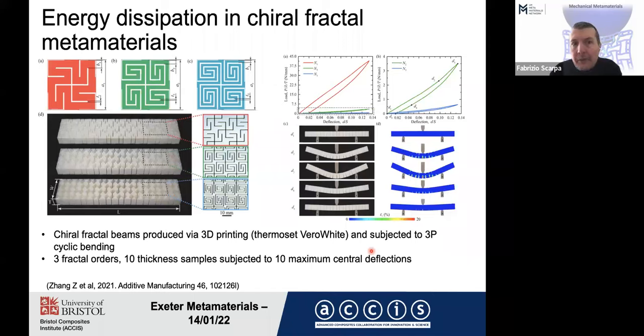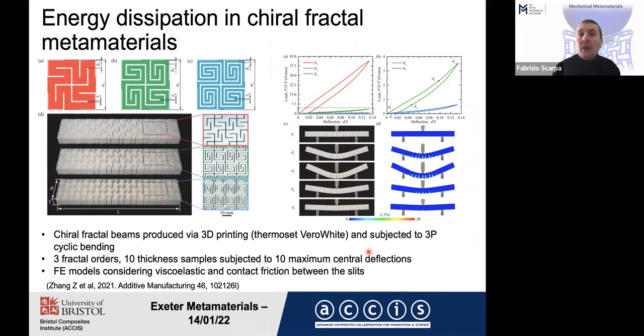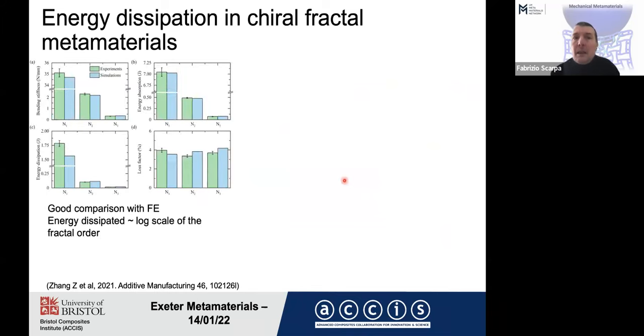We have considered 3 fractal orders, 10 samples with different thicknesses, each subjected to 10 maximum central deflections. And we have also developed finite element models that consider the viscoelasticity and also the contact stiffness and friction that exist between the vertical walls of the cells when you start to bend in the middle. The comparison between the finite elements and the experiment is quite good.